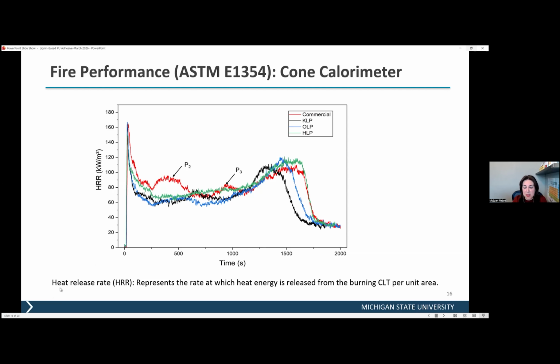What you see here is basically heat release rate, representing the heat energy that is going to be released as we are burning the CLT samples per unit area. The beginning and end peaks are where the heat release starts from the air to the wood, and at the end from wood to the air. And in between are the CLT samples. With all the lignin-based CLT samples, with the lignin-based polyurethane adhesives, it's basically almost a straight line along the way. But in the commercial adhesives, we see two major peaks here and there. This increase in the heat release that we are seeing happens through the bond line.